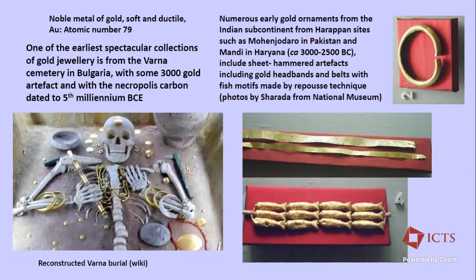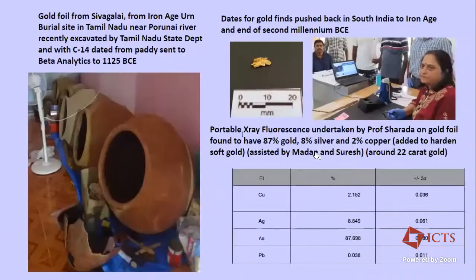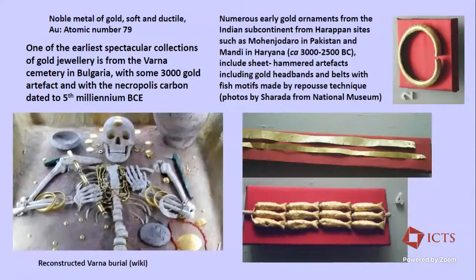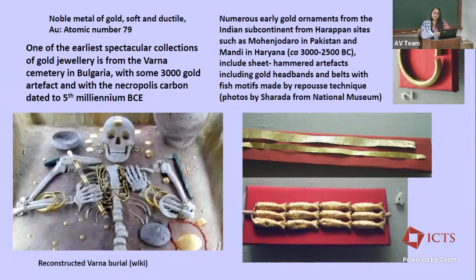But this had some 3,000 gold artifacts in the necropolis, and these had been carbon dated to the 5th millennium BC. And of course, at Mohenjo-Daro and Harappa, and in the Harappan sites, also like Mandi in Haryana, we see many of these gold headbands and belts, and also this very typical fish motif made by the repoussé technique.